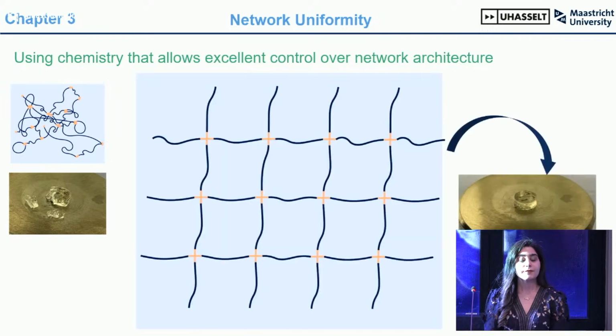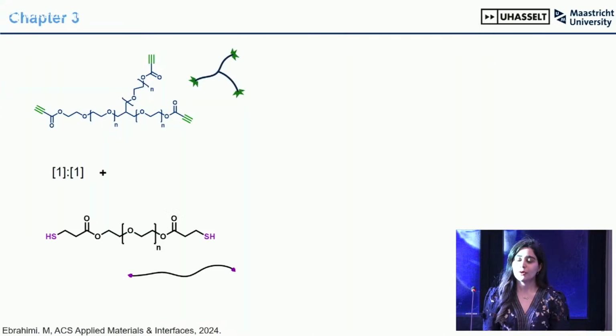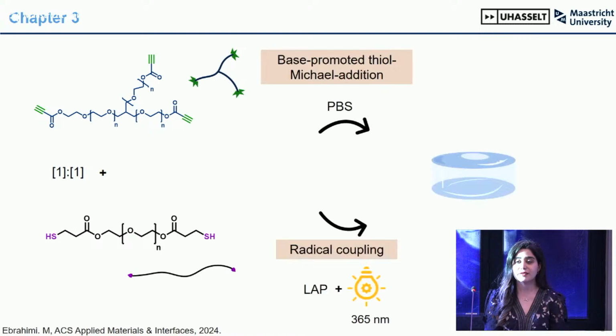To solve this, I first focus on improving network uniformity to enhance hydrogel mechanics by using chemistries that allow excellent control over network architecture. To show the important role of network uniformity, I use thiol-yne chemistry in Chapter 3. Two different categories of hydrogels were prepared using the exact same building blocks, including multi-arm PEG alkyne and linear PEG thiol, but they were cross-linked via two different pathways: a base-promoted thiol-Michael addition using PBS as a weak base, and radical coupling using a photoinitiator and light.